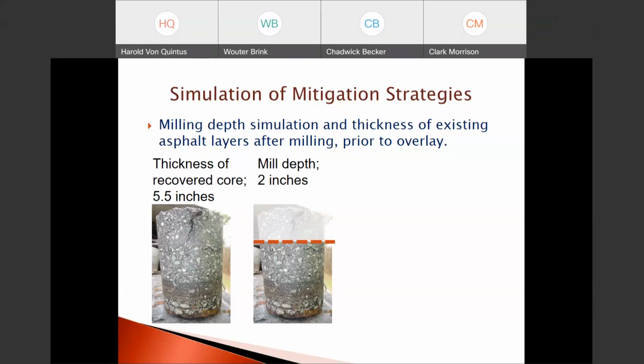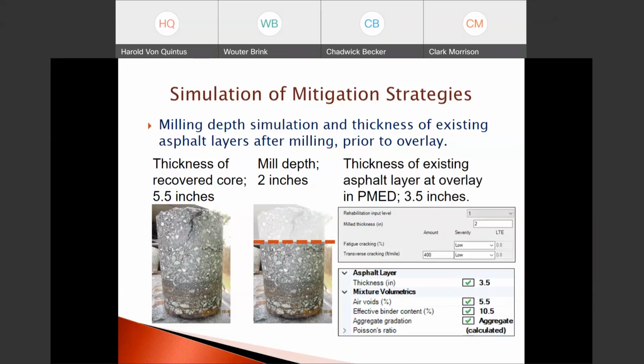We're then going to decide where we're going to mill the upper 2 inches. So we're removing the top 2 inches due to milling. So what gets entered into Pavement ME for rehabilitation level 1 or 2, as shown in the middle box, we have a mill thickness of 2 inches. And shown in the box in the bottom, we have the thickness of the existing layer of 3.5 inches. So the thickness of the existing asphalt layers is the average thickness recovered from cores minus the mill depth. So 5.5 minus 2, 3.5 inches. And that is what gets entered into Pavement ME for the existing asphalt layers.